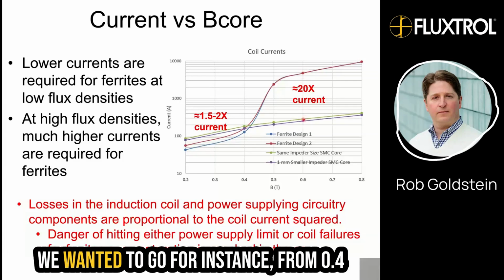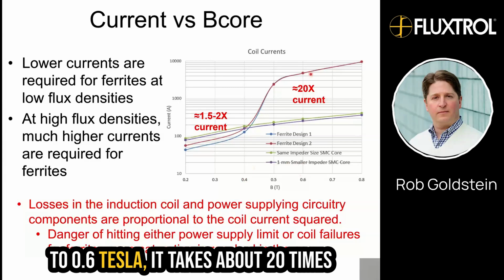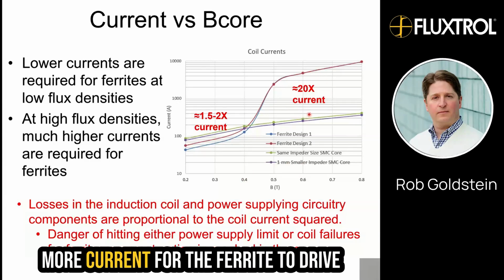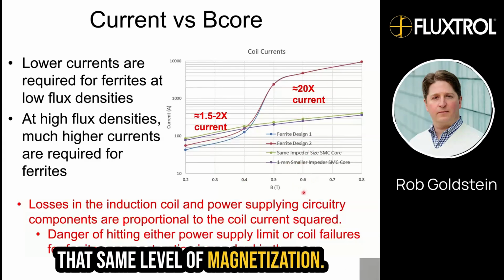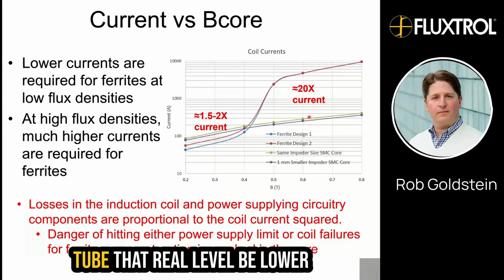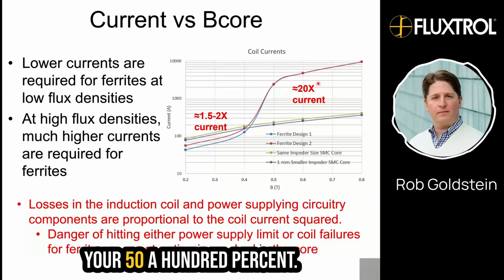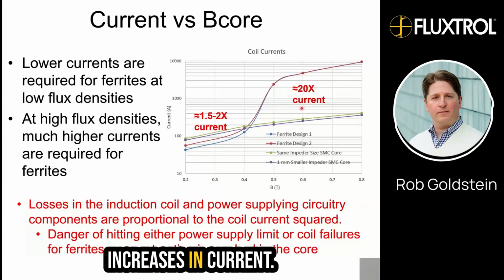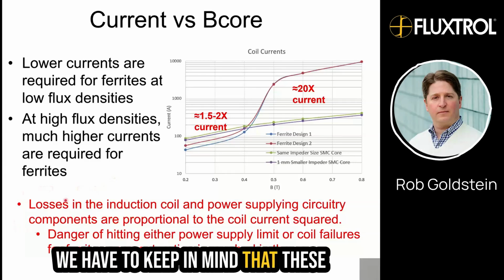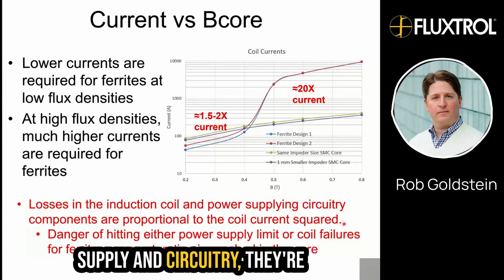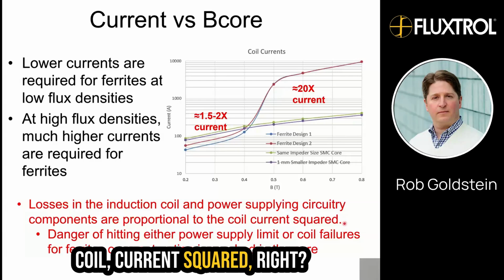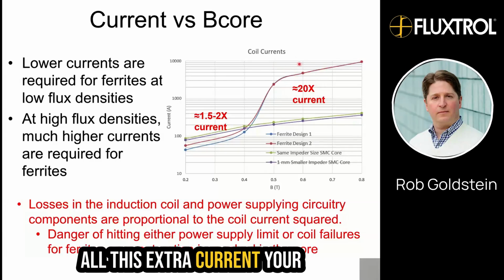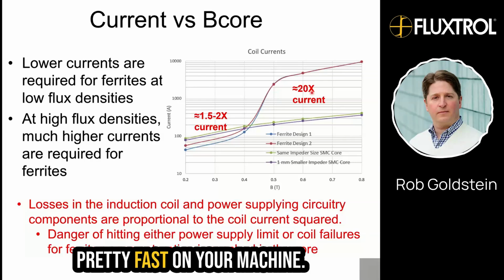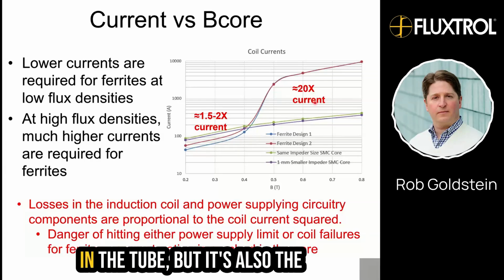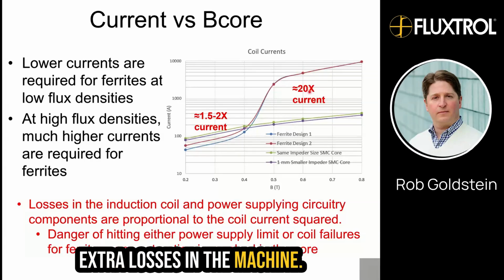And if you look up here, if we wanted to go, for instance, from 0.4 to 0.6 Tesla, it takes about 20 times more current for the ferrite to drive that same level of magnetization. Again, this does not consider the tube. That real level will be lower, but that's where you're seeing your 50 to 100% increases in current. We have to keep in mind that the losses in the induction coil, power supply and circuitry are proportional to the coil current squared. So when you have all this extra current, your overall process efficiency drops pretty fast on your machine. It's not just the extra losses in the tube, but also the extra losses in the machine.